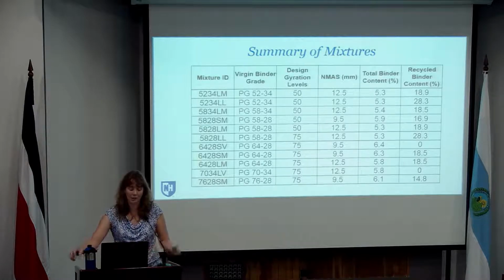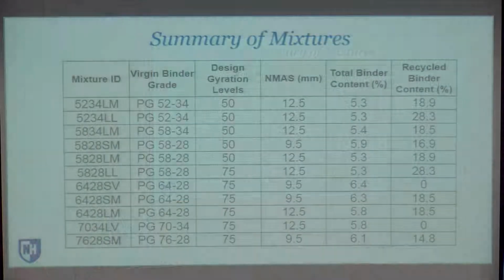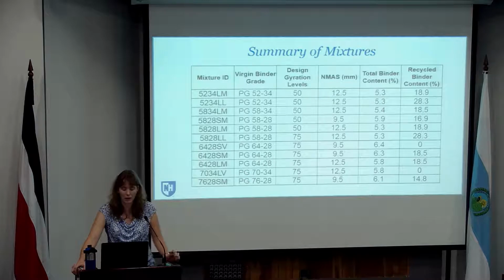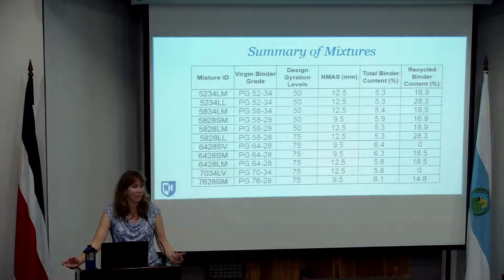So moving on to this next project, we're focusing on surface mixtures, because we're looking at aging, so we're most concerned with those surface mixtures, at least initially. We used our surface mixtures that just had recycled asphalt pavement, just the RAP from that initial project, because we do have field sections that we can look at over time, and then added some more common mixtures that are used in the state.